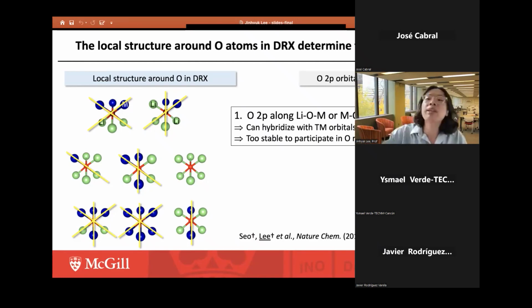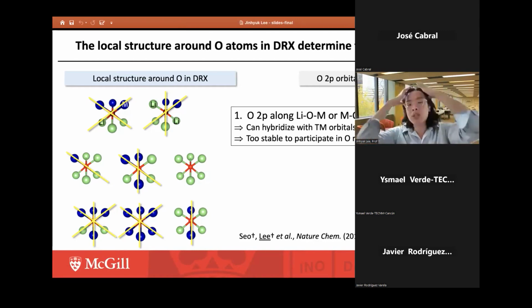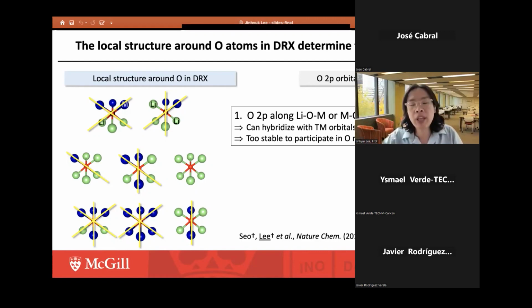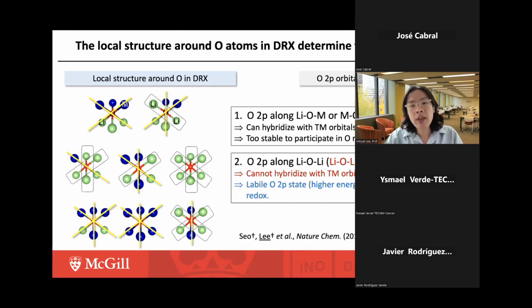Charging is like extracting electrons from some species, and these electrons are the too stable ones. So it takes so much energy to remove these electrons from these oxygen 2p orbitals, so they cannot participate in the oxygen redox process. But now if you look at the remaining geometry, we can find that actually there are